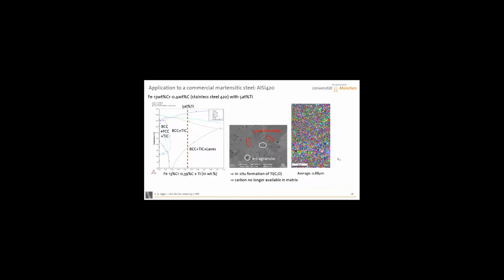The comparison is always a little bit difficult because we need to add this large amount of titanium. So you always not only do grain refinement, but you also alloy titanium. We first started with a martensitic stainless steel, which is a commercial powder you can buy, basically 13% chromium and 0.4% carbon.